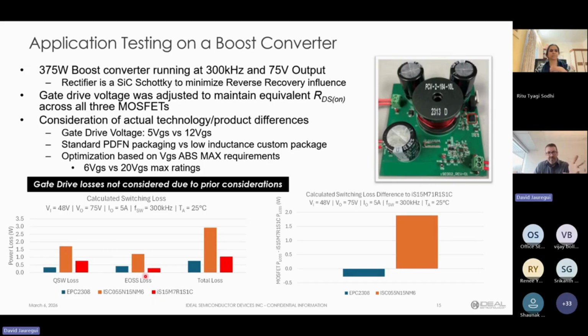From an EOSS loss, you can see that now we are in the leadership position. The GaN is slightly higher in loss than us, and then the Infineon silicon device. And then we add them all up together, you can see as a skyscraper is the silicon device, and then mathematically the EPC device is in a leadership position, and then we're just close next to it when it comes to switching loss. So if you do the math of taking this loss minus that, or the differential, mathematically we're saying that EPC is going to be ahead of us by about a quarter watt, but we're going to be ahead of Infineon's latest greatest by 1 3/4 watt. That's the theory, or at least that's the expectation.